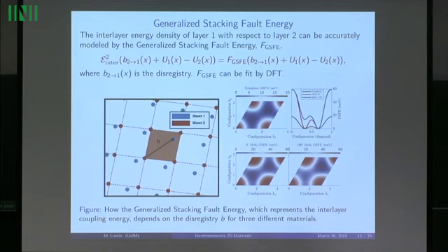If they were the same crystal and you just cut a plane through it, then the lowest energy state would be to put it back together in the original lattice. But if you start shifting, then in fact there's an energy cost to shifting the layer with respect to the other side.